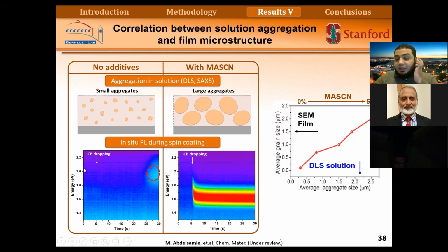So the BL at higher energy means we have quantum confinement, which is related to the formation of much smaller crystals. But if we have additives, we have slightly larger crystals at the beginning that grow very quickly into much larger crystals. And this is here the BL. It's related to the large crystal at the end of the spin coating. And we could correlate the aggregate size in solution with the final average crystal size. We have found that as we have larger aggregates in solution, we get larger crystal sizes in the final film. We can get crystal sizes on the order of microns if we use additives.